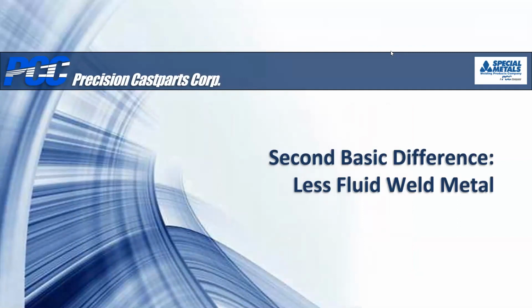And let me just leave that slide there, but just to say, several of these materials, the contaminants, like sulfur and phosphorus particularly, do form eutectics, which are lower melting point combinations than the base metal. So they're the last to solidify, and they can cause you big problems. The others are low melting point metals. And we didn't have mercury on our list, but it is possible to have mercury contamination, and it's a liquid at room temperature. So you can imagine what mercury would do to your material. So anyway, just keep it clean. Get it clean and keep it clean.